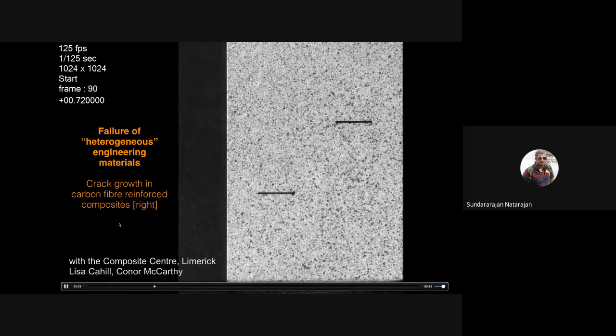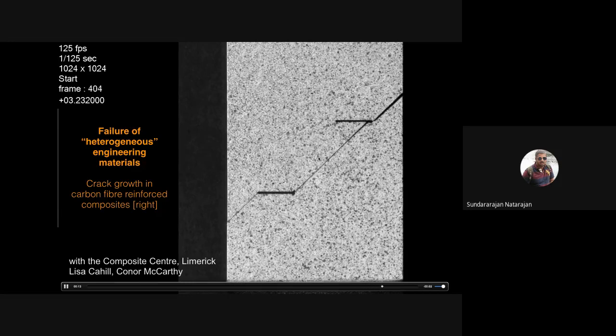You'll see that the crack starts to propagate from this line, and it fails in an instant. And this is a typical quasi-static brittle failure. I can see that at about this frame, the crack just started, and you can see there are some fibers that are also hanging out because of the fracture.